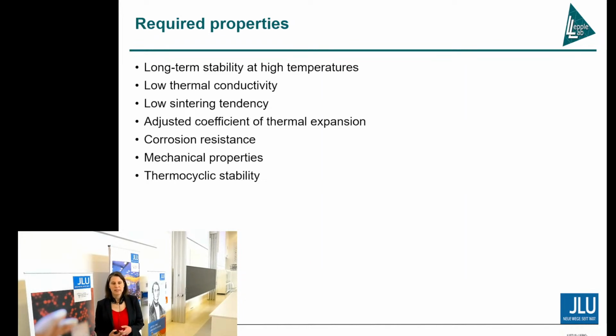So regarding the properties such a material, for example a thermal barrier coating, has to achieve, first is the long-term stability at high temperatures, of course, then a low thermal conductivity, because we want to protect the nickel-based substrate material from the high temperatures. We also want to have a low sintering tendency, because usually we have this columnar structure or porous structure to further reduce the thermal conductivity, and we want to maintain this structure. Also, we need an adjusted coefficient of thermal expansion for the base material, high corrosion resistance, mechanical properties, and also